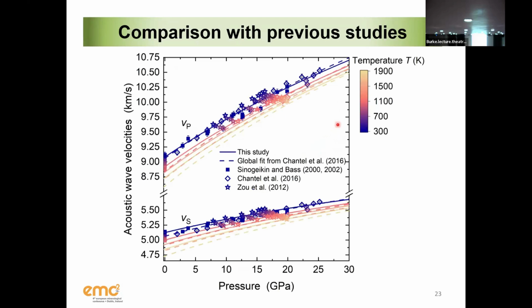Then, of course, you want to compare your data to know if you are doing something wrong. The only thing I want to stress here is that if you look at the solid line, you can see it fits better the data collected by Sinogeikin at room pressure and high temperature than the model that we published with Chantel in 2016. That model was based on ultrasonic multi-anvil data, which were collected only up here because we cannot collect at low pressure: you need to close your sample in the multi-anvil and close all your cracks to have proper ultrasonic data. So up here the agreement between these two models is good because we had a lot of data also with Chantel. Down here it is not so good because we were missing data, and now we have it.